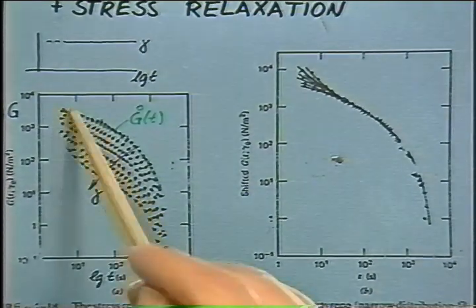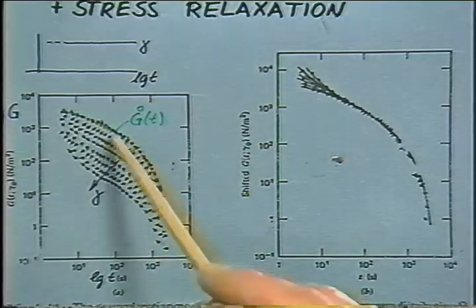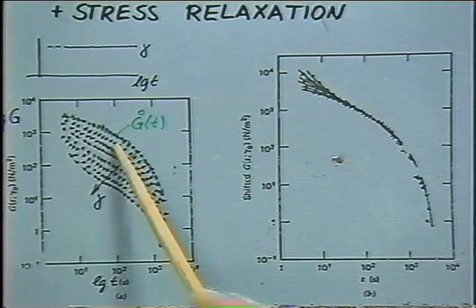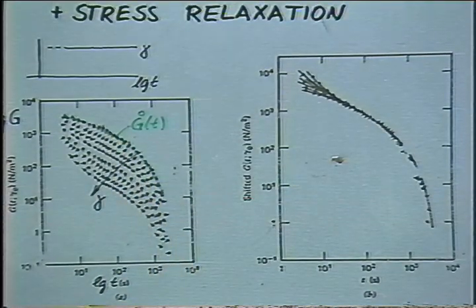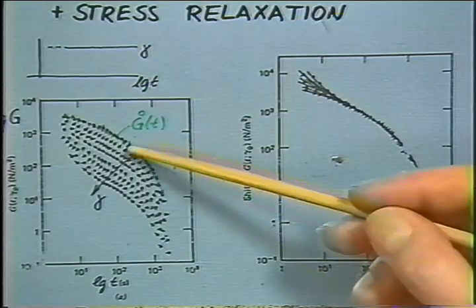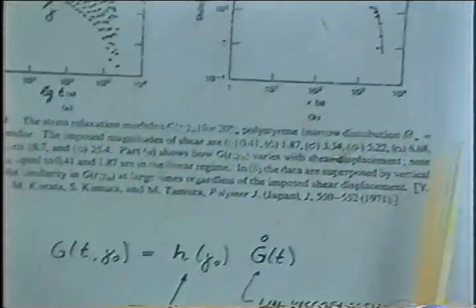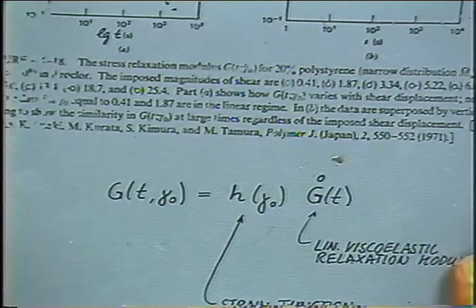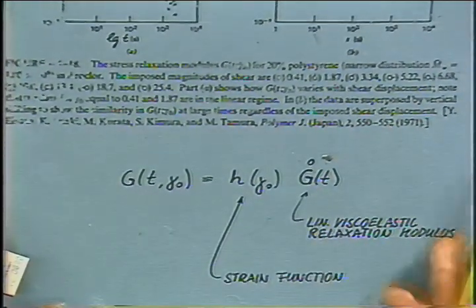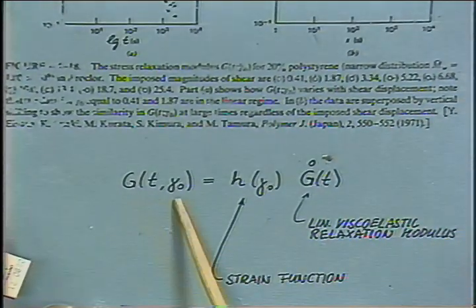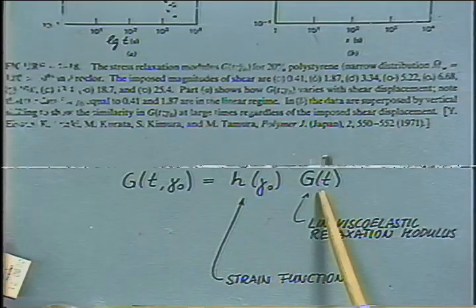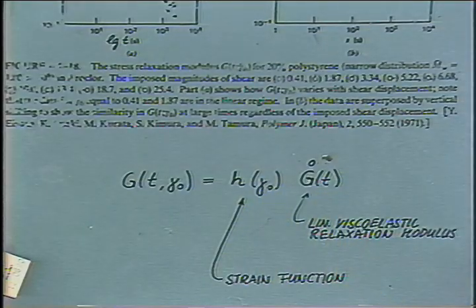And this is the relaxation modulus at small strain, and at large strain, somehow the modulus is reduced in value, and Osaki's result was the factorization of the relaxation modulus into a strain function and a time function. And we would like to measure that now.